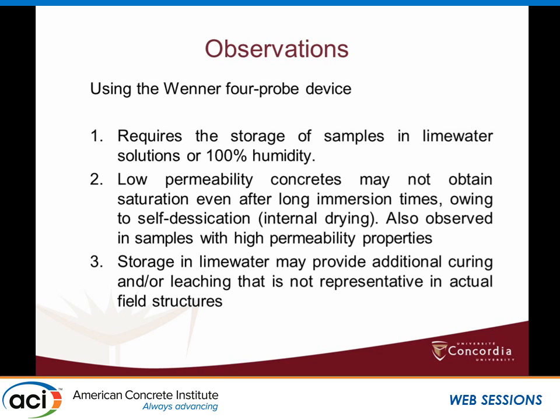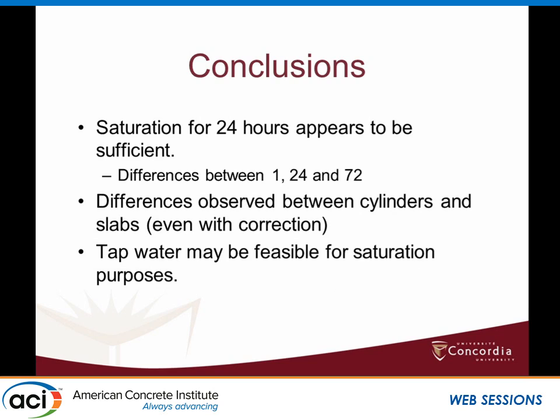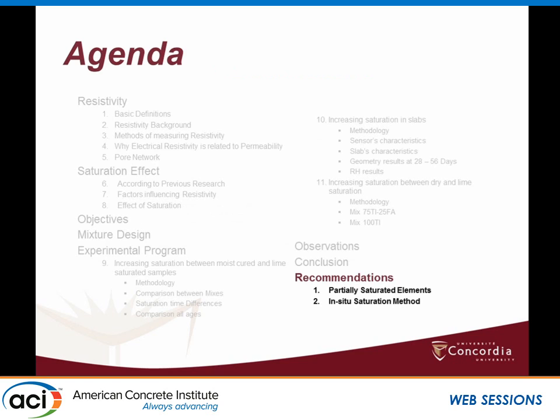So until now, we have some conclusions for this 6-month work: that saturation in the lab can be accomplished with just 24 hours. There are differences observed between cylinders and slab, although we apply the correlation factor. Tap water is as good as a lime water solution. However, we want to